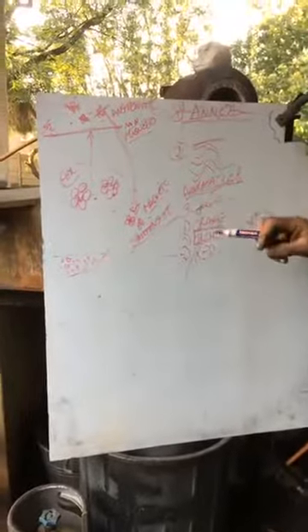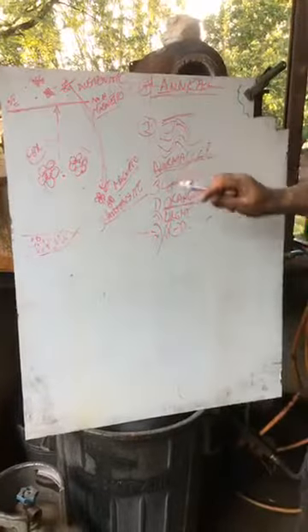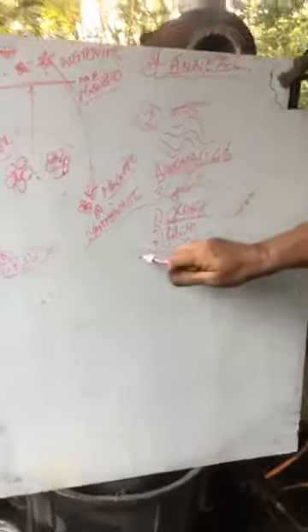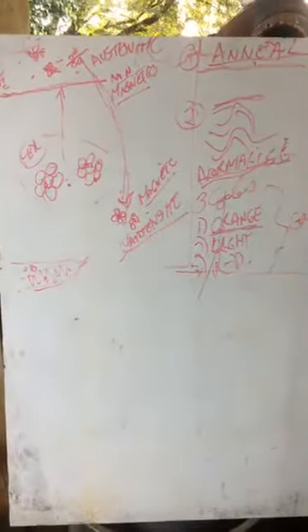But if you're working with coal or charcoal, it's very difficult, because you really have to watch that temperature. The grain can shoot off that grid so quickly and become a larger grain and destabilize the whole mess, and it's going to become hard and crumbly. It's not going to be good. So this is easy in gas, it's hard in coal or charcoal. So anneal it, normalize it, and then we're going to harden it. So this is hardening. So 1, 2, and 3 hardening cycle.